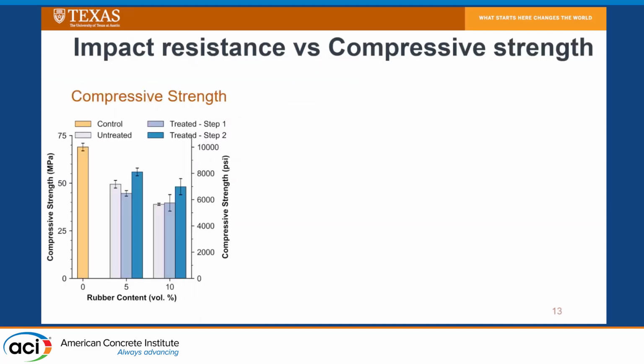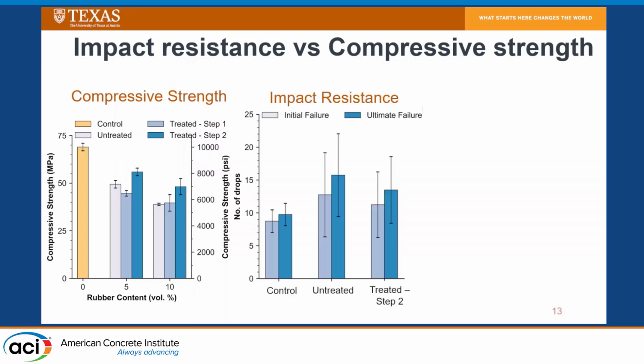When we look at impact resistance versus compressive strength, another thing I want to point out is that with respect to compressive strength, as we go from light blue to dark blue, let's actually say from untreated to the dark blue, we can see that we get this increase in compressive strength, right? And this is the same whether we have 5% rubber or 10% rubber. When we look at impact resistance, as we go from untreated to treated, we see that we don't necessarily get this increase, right?